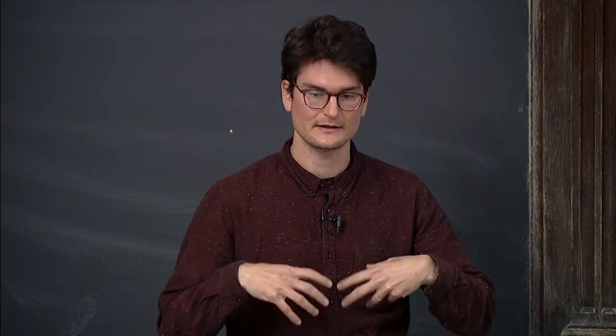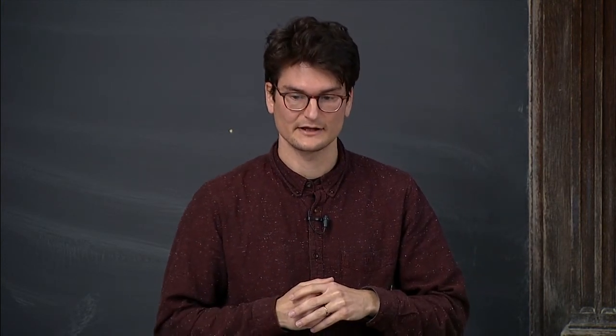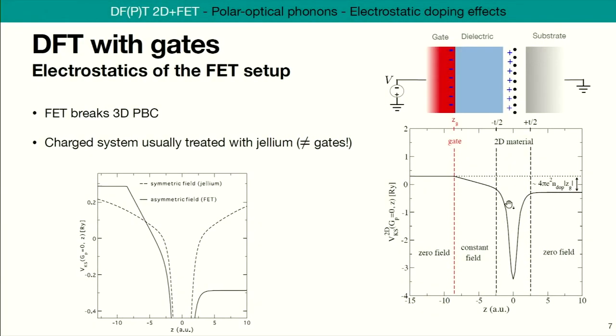Okay, there is still a way to charge a material in DFT, and that's the so-called jellium. So that's a uniform background of compensating charges. And it kind of works, but it's quite different. If we zoom in on the region around the material here, oh yeah, and I forgot to mention that this dip here is what you get when you do a DFT simulation. It's kind of a potential well in which the electrons go around the material. So anyway, if you zoom in on this thing, this is what you're supposed to get: linear on one side and constant on the other. But if you look at the jellium, what it does, it has this symmetric and quadratic dispersion outside. So the electrostatics are very different.